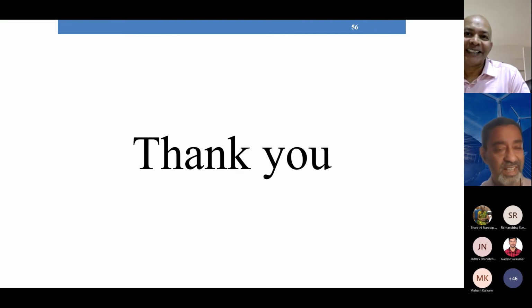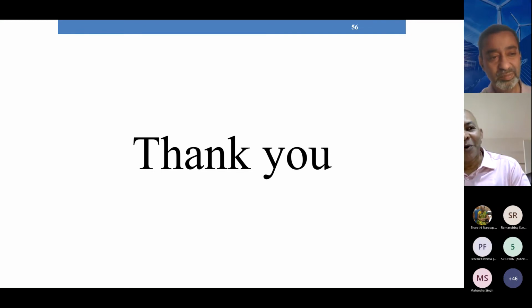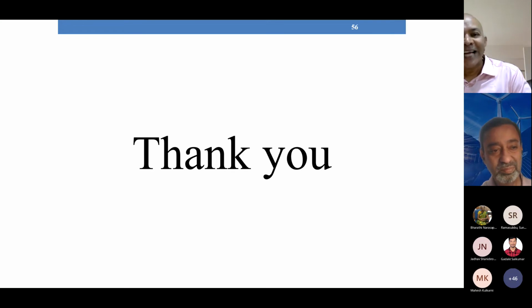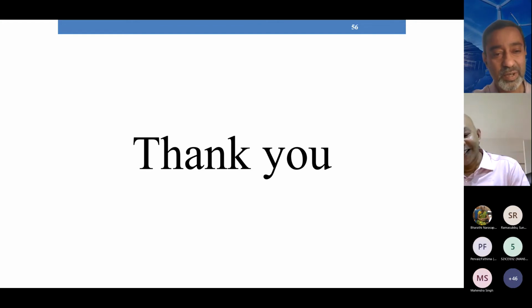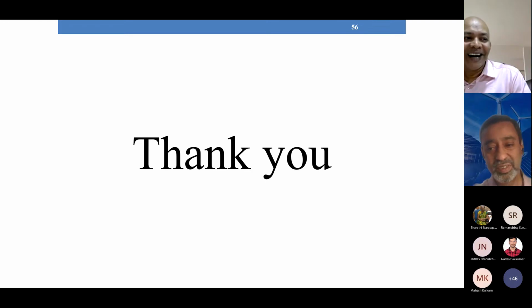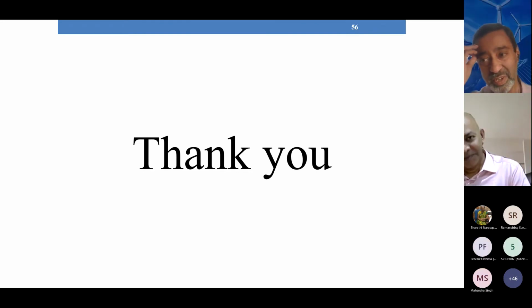What does the literature say? Does it help? In thermal imaging, what the literature says is that in concrete it will be very difficult, because the change in temperature is not large enough to be captured by an infrared camera. However, I'm trying it out. Especially when you perform a fatigue test, the heat generated is not sufficient to be captured, or maybe I should use a very sophisticated infrared camera. What is the NETD of your camera? Is it 0.05 Kelvin? I don't remember the specs, but it's at the lower end of the higher-end cameras. Okay.